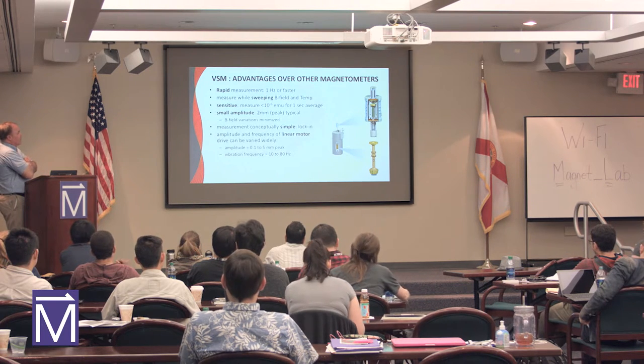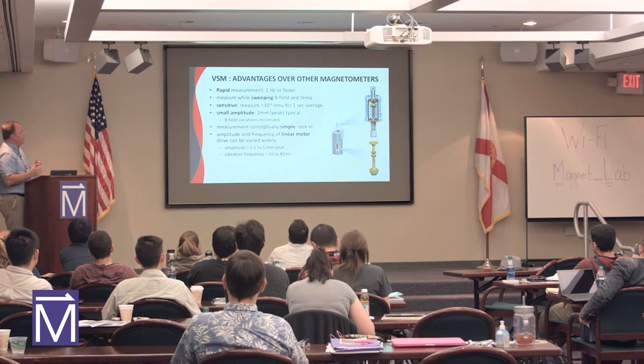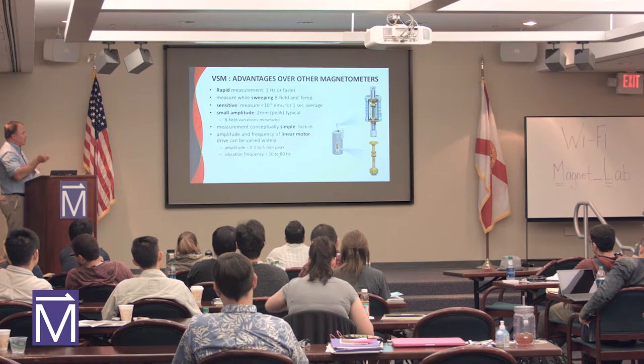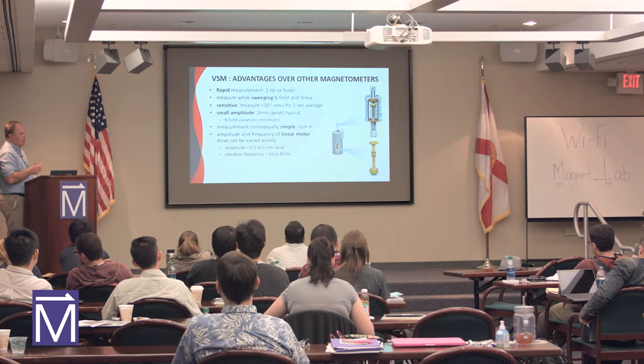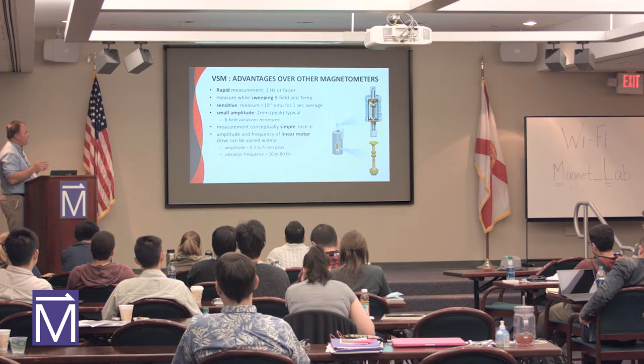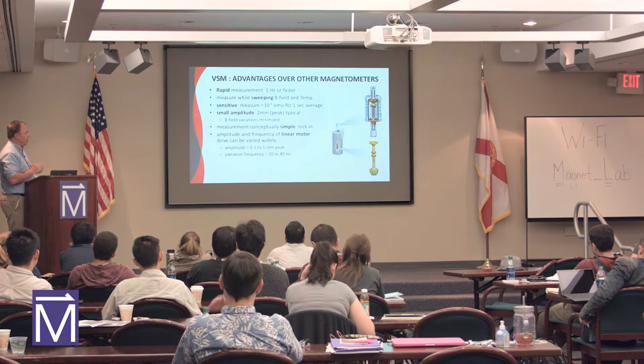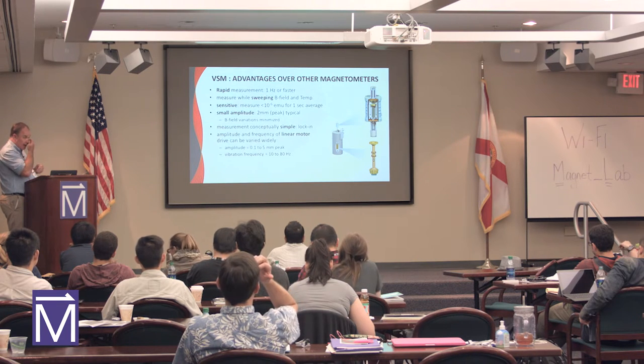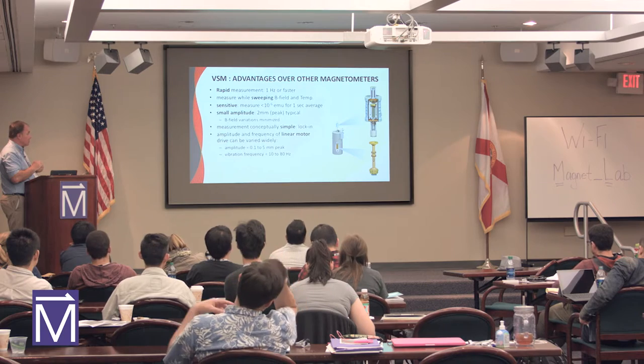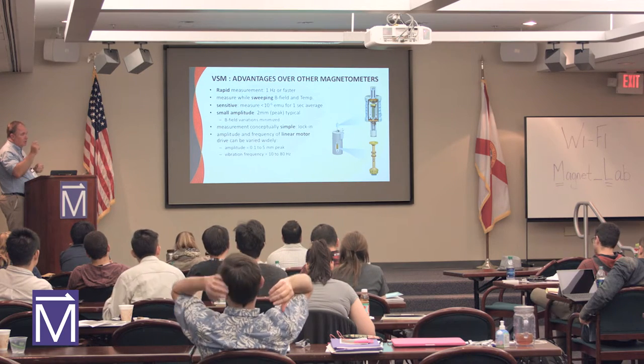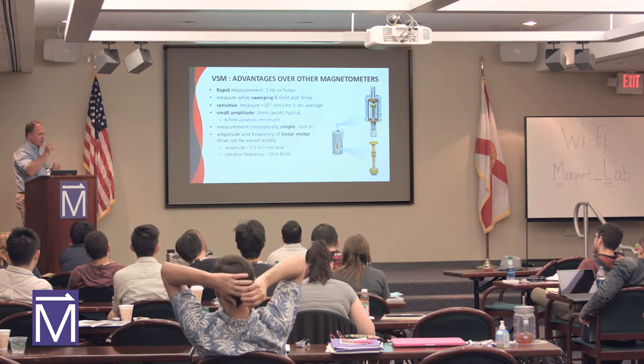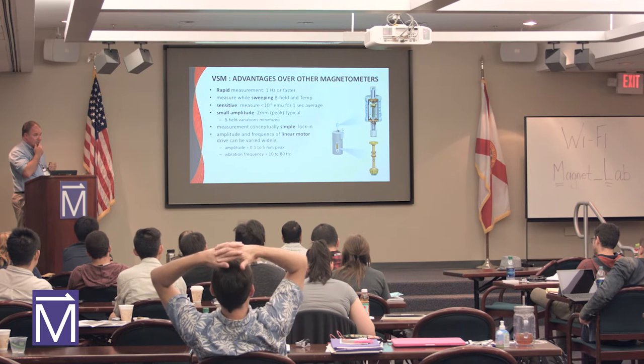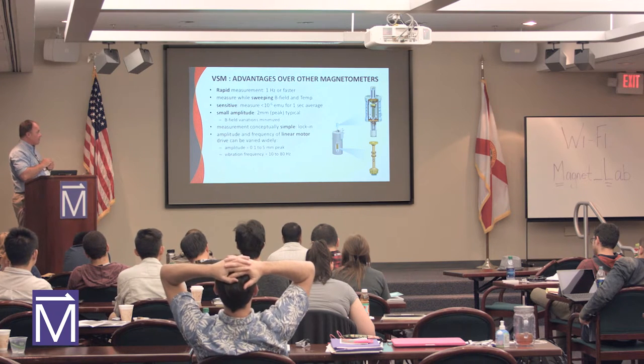So the VSM over other types of magnetometry: fast measurement. The sample's moving fast through the magnetic field. You're taking measurements while you're sweeping the sample through the field. 10 to the minus 6 EMU in a less than a second measurement time, so it's a sensitive measurement. You're moving it through a small amplitude, so it's only moving a couple of millimeters through the magnetic field.